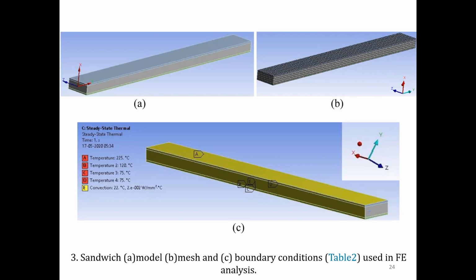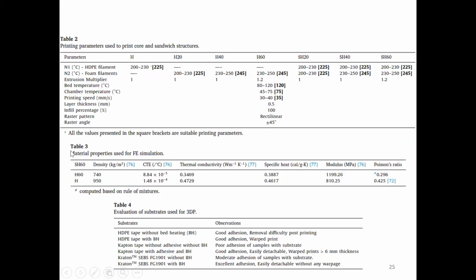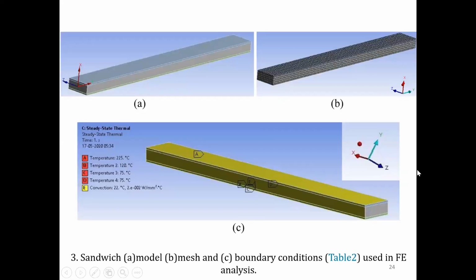And in pre-processing, the properties of skin and core were defined, and then we fed them. I think those properties are available here in table 3 for as far as density, CTE, thermal conductivity are concerned. And the sample we printed and utilized for finite element analysis had a length of 180 millimeters, 18 millimeters wide, and total 8 millimeter thickness, wherein 1 millimeter skin on bottom and top are out of these 8 millimeters. So core is about 6 millimeters.